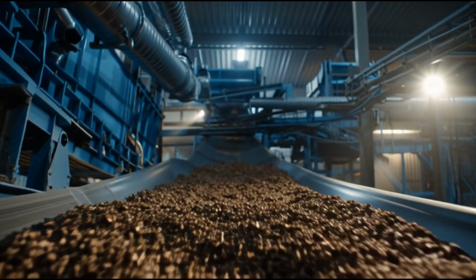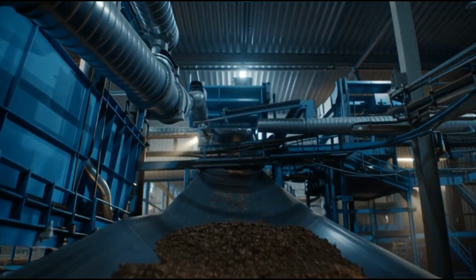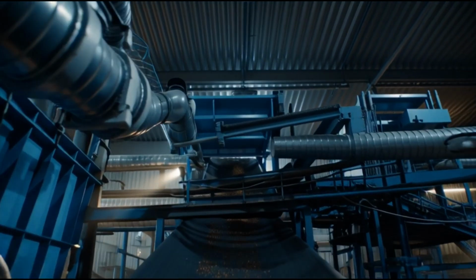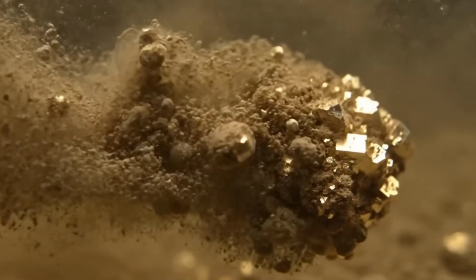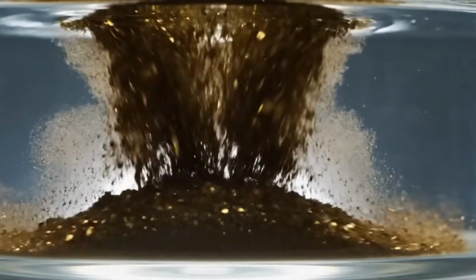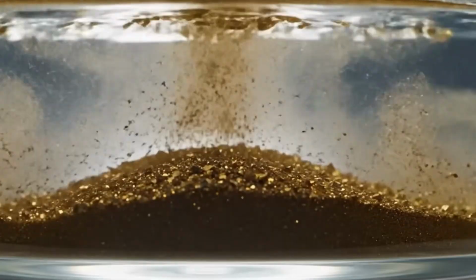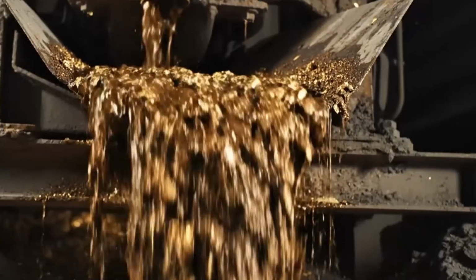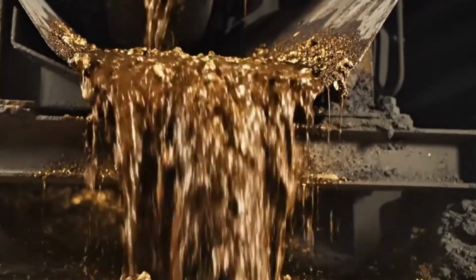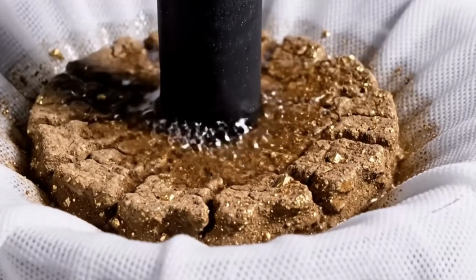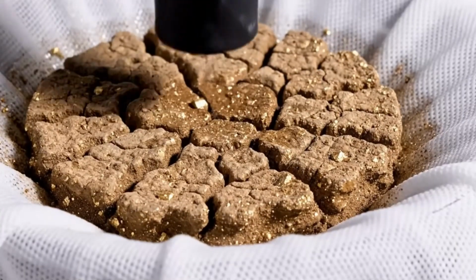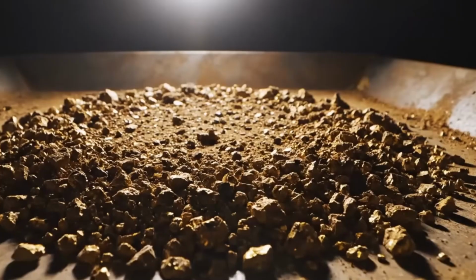To remove the gold from the carbon, the plant runs a process called elution, or stripping. The carbon goes into a pressurized tank and gets flushed with a hot caustic soda and cyanide mixture heated to roughly 110 to 130 degrees Celsius. This hot wash pulls the gold off the carbon and into a fresh liquid known as the pregnant eluate.